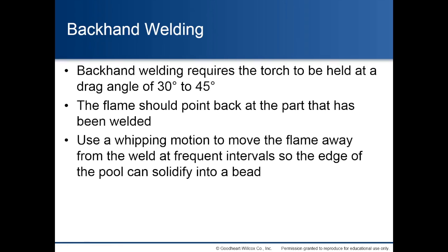Backhand welding. Backhand welding requires the torch to be held at a drag angle of 30 to 45 degrees. The flame should point back at the part that has been welded. Use a whipping motion to move the flame away from the weld at frequent intervals so the edge of the pool can solidify into a bead.